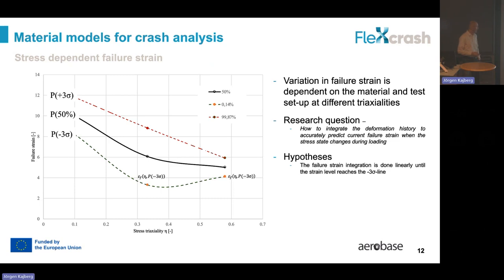Our hypothesis is that when you calculate your failure strain, because this is dependent, in a crash analysis you don't have a constant stress triaxiality. It will vary, so you need to take care of that. But we do that, you can say, linearly. As an example here, if we start with uniaxial tensile at time T1, we deform it, and we are 40% from the -3 sigma line. Then when we go to the next time step with another stress triaxiality, in this case close to plane strain, we start at the same distance from the -3 sigma line.